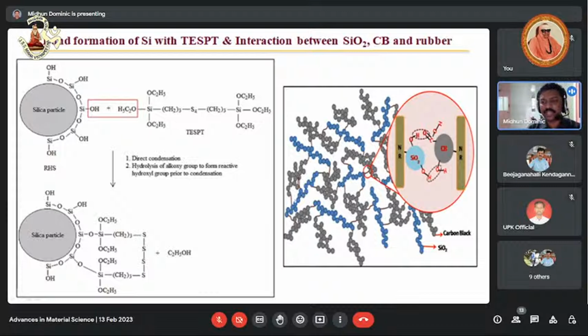So in the case of commercial silica and carbon black, carbon black also has some COH and OH functionalities, and silica has OH groups. So there is hydrogen bonding between the functionalities of silica and carbon black, so there is network formation. This three-dimensional network formation is possible between carbon black and commercial or precipitated silica, and this three-dimensional network is responsible for transferring the stress. Because of this network, they have higher mechanical properties. But this kind of network formation is not possible with BJRHS.